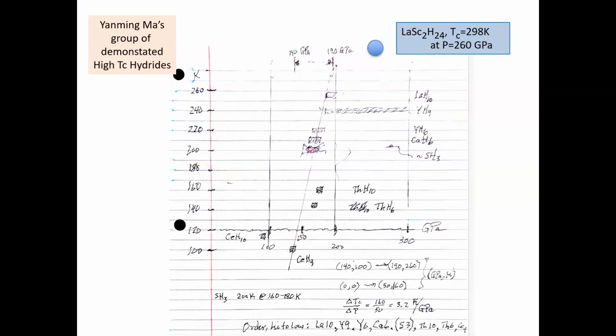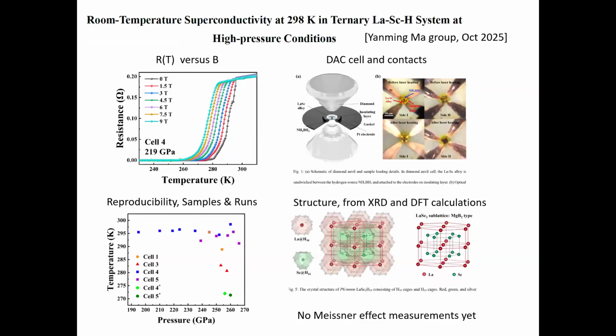Okay, so this one is lanthanum scandium 2 hydrogen 24, which was posted on the archive again, October of last year, 298 Kelvin. That's the temperature right in this room, give or take, at a pressure of 260 gigapascal. As I showed in the previous group slide, this is significantly larger than the 200 or 180 or whatever of the other high TC metal hydride materials under pressure. But these are different samples or different runs. So it's repeatable, and these experiments at this high pressure, often the diamonds break and you have to start over. So these are not exactly reproducible, but this is a very good indication that in many cases they get 295 to 298 degree superconducting transition temperature.